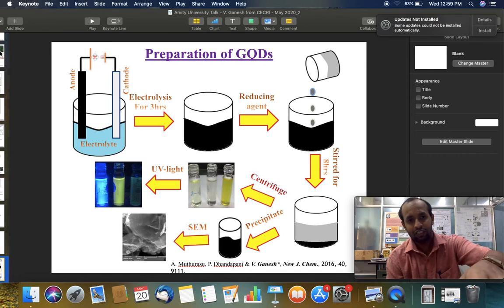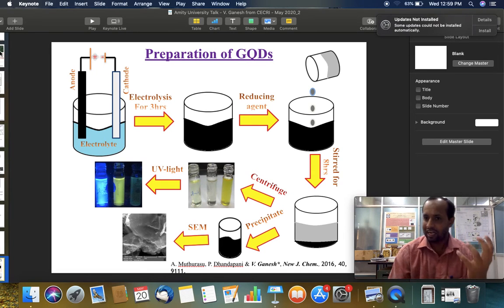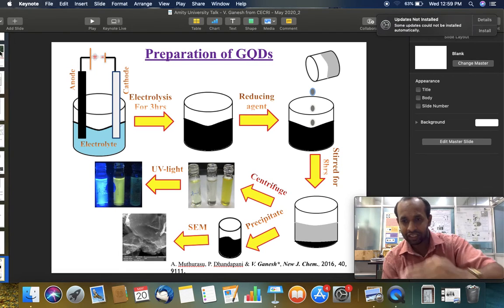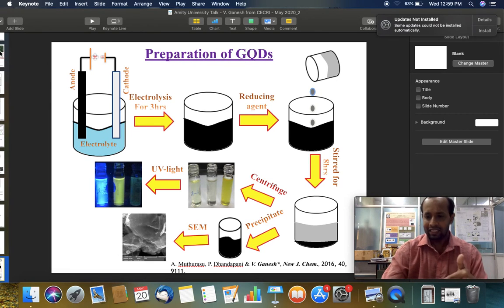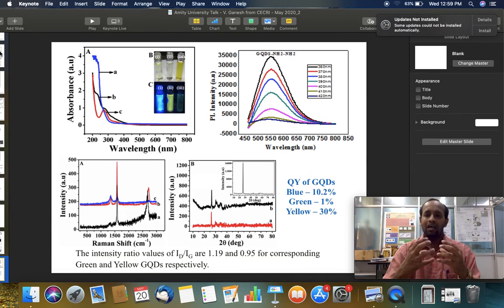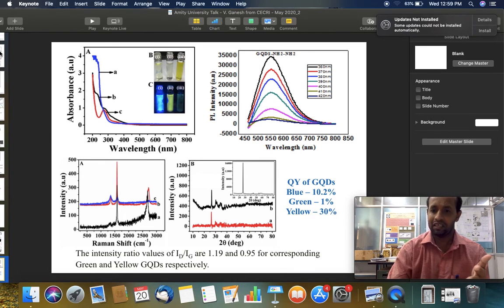Okay, so what we do is an electrolysis, you take the electrolyzed electrolyte part, add a reducing agent and stir it for a specified time duration. And after a certain time duration, which of course depends upon the nature of the reducing agent, you are able to tune the emission colors which arise from the supernatant to green, yellow, blue, etc. And the settled precipitate is nothing but your RGO, reduced graphene oxide. Okay. So in fact, we analyzed the mechanism behind such formation. We also measured the quantum yield of such fluorescent graphene quantum dots.